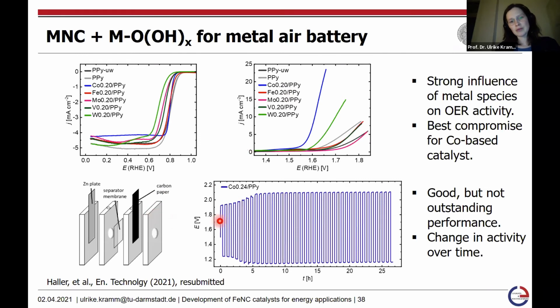So this is then the performance of the catalyst, where you can see that within the first, typically between 6 and 10 cycles, we unfortunately see an increase in the potential gap. But the good point is that at the moment it looks like this is more related to our cell design, as for a very different catalyst material we observe almost exactly the same trend here. So this seems not to be related to a decrease of the cobalt type catalyst material.